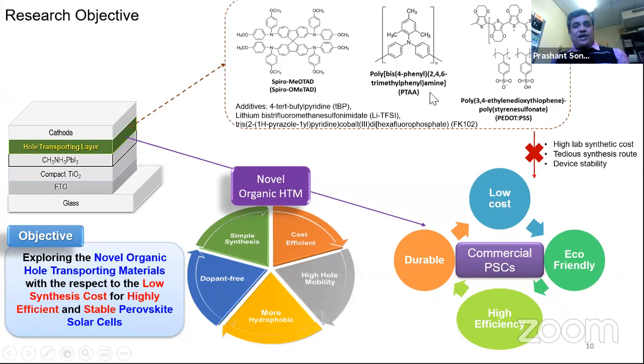And again, looking at other types of materials people use as hole transporting, particularly the polymer PTAA, polytriarylamine, which is a very expensive material, even 10 times more expensive than gold. And then we have PEDOT:PSS, which is poly(3,4-ethylenedioxythiophene) polystyrene sulfonate, which is acidic by nature.